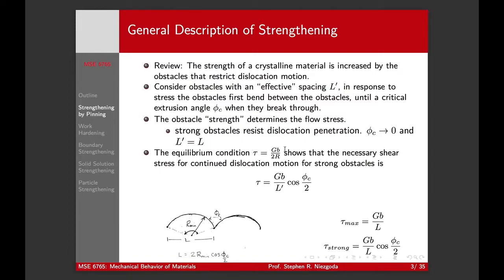when we're moving dislocations around things, we need to remember our line tension of a dislocation, right? Remember, this is the stress required to bend a dislocation to a given radius, because as you bend a dislocation, you're creating more dislocation line length. So there's a natural force to reduce the line length by making the dislocation straight. But by applying a stress, we can bow that dislocation out.